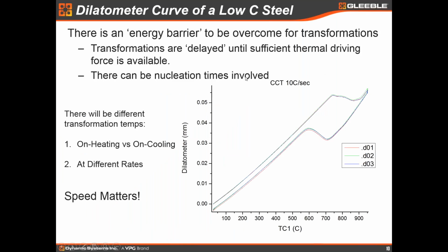So one thing to notice on all these curves is that there is an energy barrier to be overcome for transformations. So once we get to that point where ferrite and austenite are equally energetically favorable, we have to provide a little extra energy, either overheating or undercooling, depending on which direction we're going, to make that transformation happen. So what this means is that transformations are delayed a little bit until there's a sufficient thermal driving force to drive that crystallographic transformation. And there also can be some nucleation times involved.